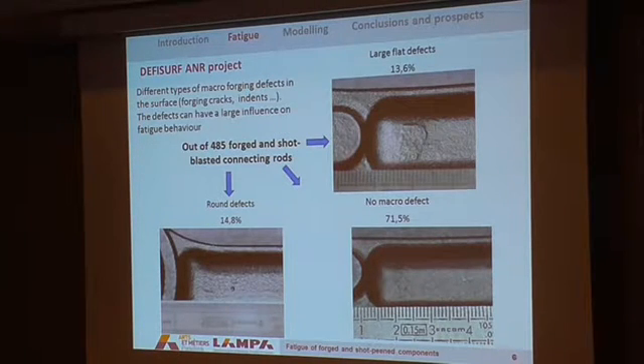And for instance, if I take around 500 forged and shot blasting connecting rods directly from the production, and I try to make simple statistics about the kind of defects that can be observed, you see here that for 14% of the connecting rods, you can see that kind of defect. It's nothing else but some scale encrusted at the surface of the part, and some round defects for 15%, and the majority without defects. So we're going to have a look at what happens with those defects on the surface.